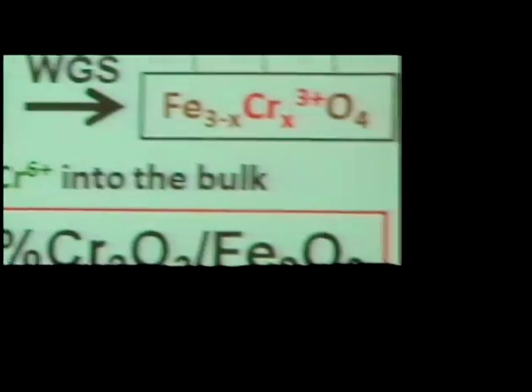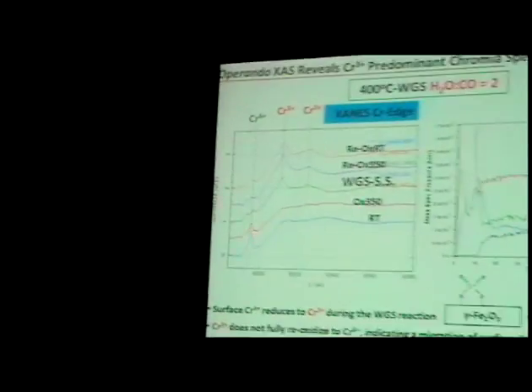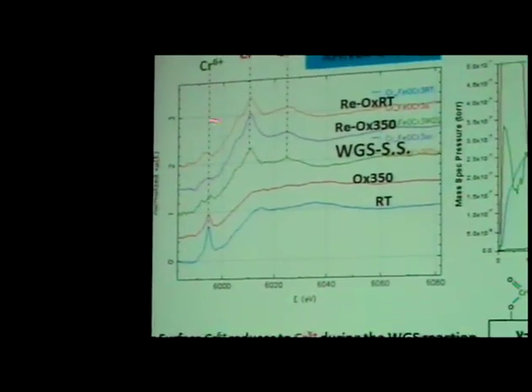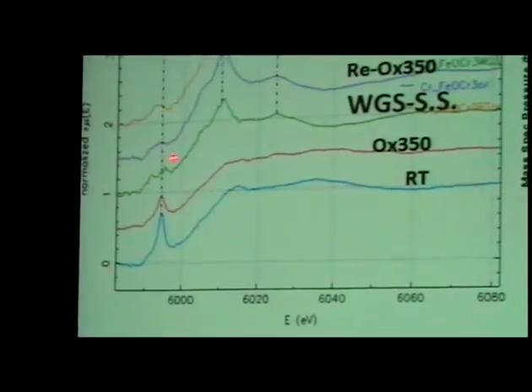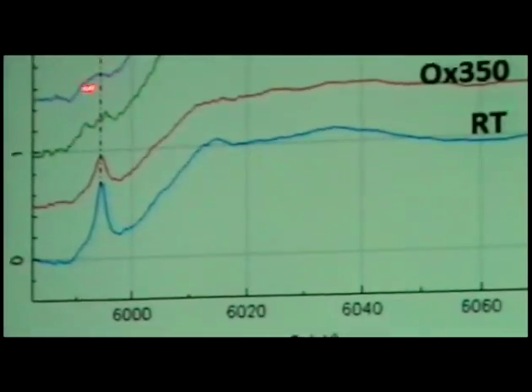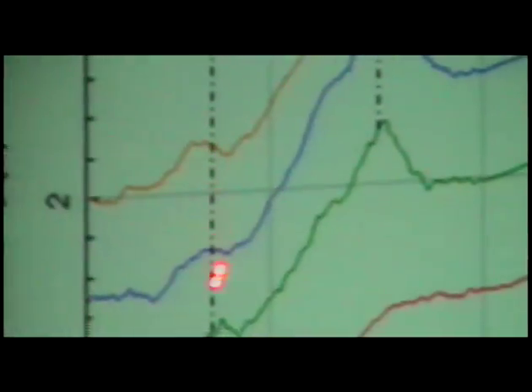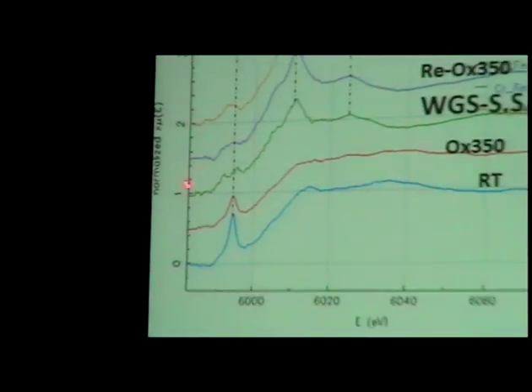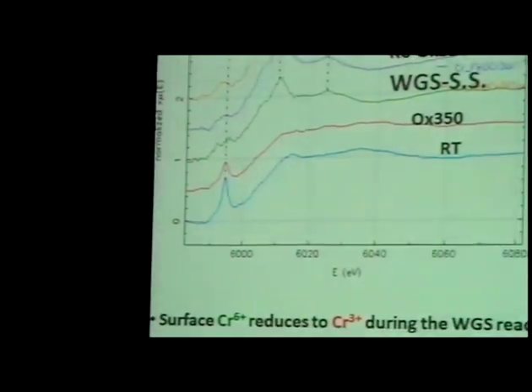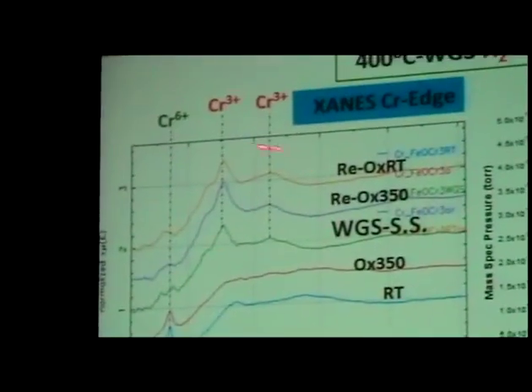Now we reoxidize it at the end to see if the original chromium 6 comes back. As you can see, it is not coming back. So maybe just slightly coming back up here. This is the water gas shift, and this is the reoxidized catalyst. Okay? A slight increase in this feature. So most of the chromium here apparently is lost and stays, as you can see here, as chromium 3.